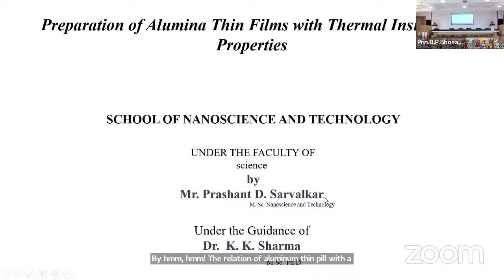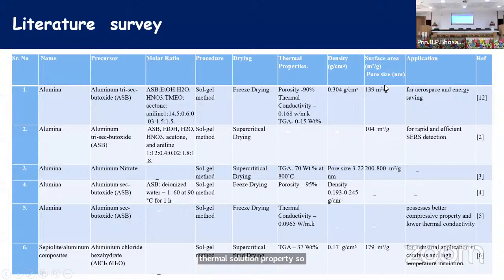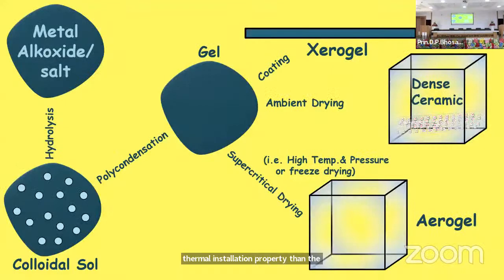Among the other precursors used for alumina thin film, we separated out some alumina precursors by their structure and their results by literature survey. As per our literature survey, there are two ways to synthesize alumina thin film. One uses an aluminum alkoxide precursor and the second is an aluminum salt precursor. Here we discuss the aluminum alkoxide precursor, that is aluminum tri-sec-butoxide, and the aluminum salt precursors, aluminum nitrate and chloride. According to our literature survey, aluminum salt based precursors show higher thermal insulation property than the aluminum alkoxide. So we use all three precursors for the testing of the aluminum thin film preparation.